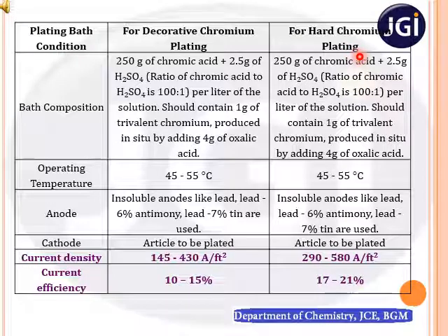That can be done by controlling two factors, current density and current efficiency. If we vary these two conditions, we can achieve the required thickness. The remaining parts are the same for both cases, decorative as well as hard chromium. With this idea, let us discuss the bath composition. The electrolytic bath contains 250 gram of chromic acid plus 2.5 gram of sulfuric acid. The ratio of chromic acid to sulfuric acid is 100:1 per liter of solution.